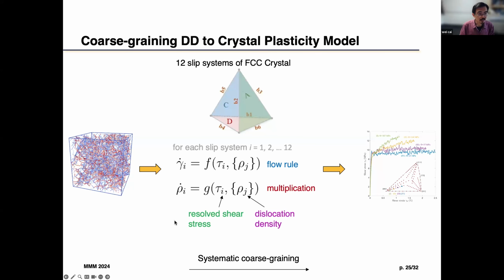So we can look at, let's say, single crystal plasticity models, right? In the past, it has been sort of just, you propose a certain form and then you try to fit it with experiments. But now, because we can do a large number of DD simulations, we actually get a lot of data, like 10 terabytes, recording all the details of all the simulations, loading all different hundreds of orientations. So maybe from those data, we can systematically coarse grain and construct constitutive equations, both in terms of fitting the parameters and in terms of questioning whether the form is correct.